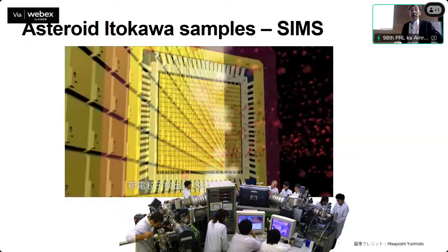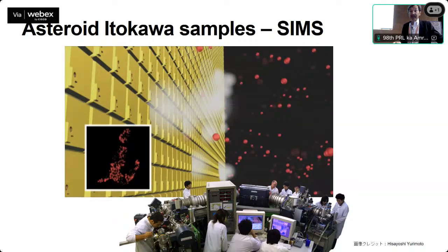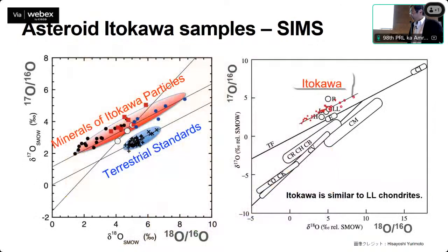So oxygen has 3 isotopes: oxygen 16, oxygen 17, oxygen 18. Therefore, we can count 3 oxygen isotopes simultaneously. Then I make this diagram. The horizontal axis is the oxygen 18 over oxygen 16 isotope ratio. The vertical axis is the isotope ratio of oxygen 17 over oxygen 16. And this is the region of the terrestrial samples. And the red region is the oxygen isotope compositions of Itokawa samples.